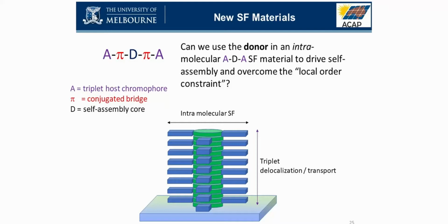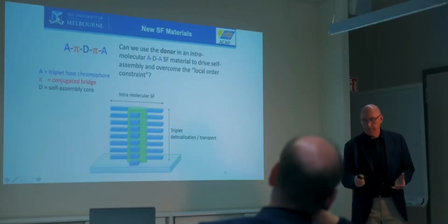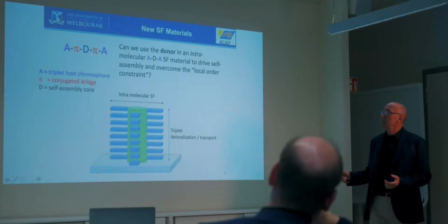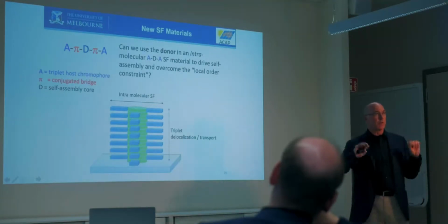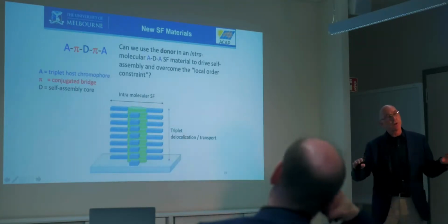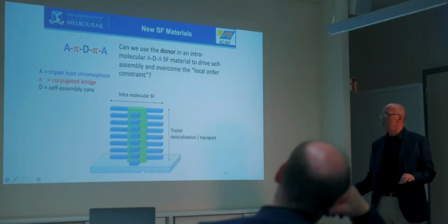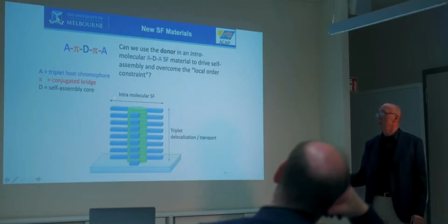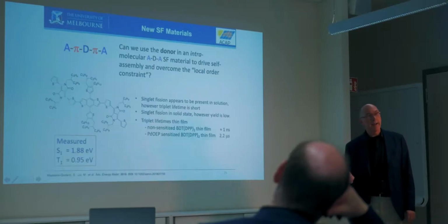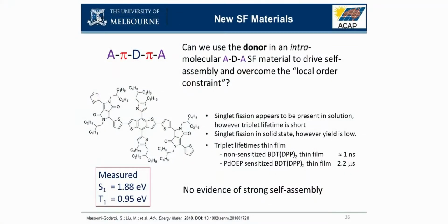Okay, so we wanted to basically use this sort of a structure, and we have this core here, which is going to be driving our self-assembly. We wanted to have some sort of linker or a bridge if needed, and we wanted this acceptor or this triplet host. This is where our triplets are going to end up. So we wanted this structure so that we could have then some self-assembly. Intramolecular singlet fission. Okay, so we went back and thought about what we can do. We knew this core was in our materials I talked about earlier. This promotes strong self-assembly in those materials.